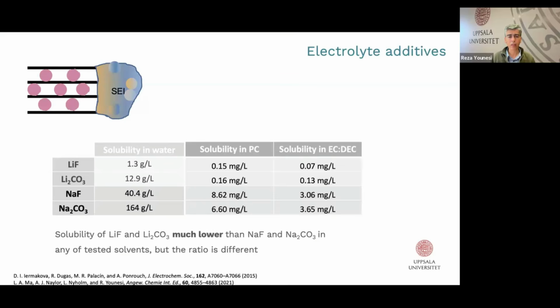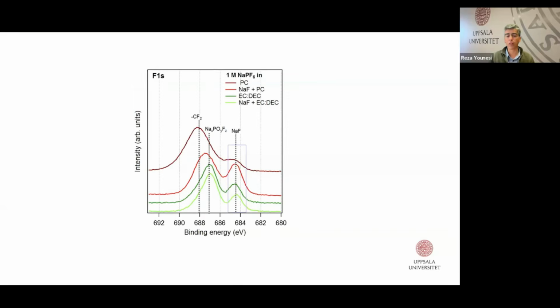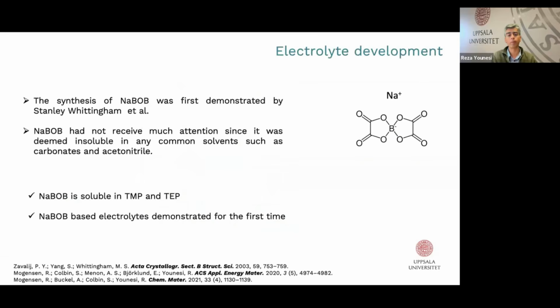The solubility of lithium fluoride in PC is higher than in EC:DEC, which means we expect more solubility of lithium fluoride in PC. So when we add sodium fluoride into the electrolyte solution and saturate it, we don't allow the sodium fluoride that is electrochemically formed to dissolve in the electrolyte solution - it remains in the SEI, and we can detect it by XPS. While in EC, the solubility is very low, so perhaps the addition of sodium fluoride won't have any major impact on the composition of SEI.